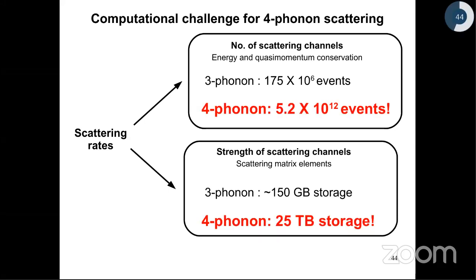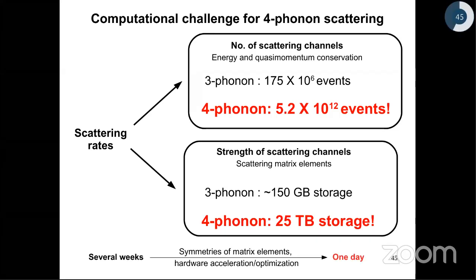But if you look at the corresponding numbers for 4 phonon scattering, the number of allowed events go up by 4 orders of magnitude, and the corresponding storage also increases significantly. So when I first implemented this code, the first version actually took me several weeks to get a converged thermal conductivity number. But over the past couple of years, I have implemented several symmetries of the matrix elements involved in the scattering rates, strength calculations, and also incorporated several hardware acceleration features to bring down the computational cost and the computational time to an order of 1 day.